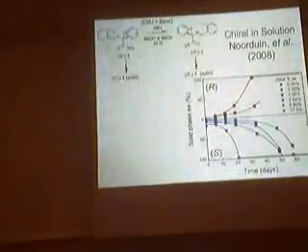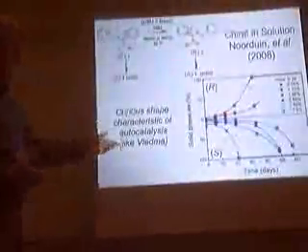Okay, now here's the plot which he showed you, and remember you start with a very small enantiomeric excess in favor of either the R or the S, and in time it evolves to 100% enantiomeric excess. It has a curious shape which is acceleratory, so it's autocatalytic. It's just like what Kondepudi found in the case of sodium chlorate, that it's autocatalytic. So it's not a normal chemical reaction which slows down as you near equilibrium.